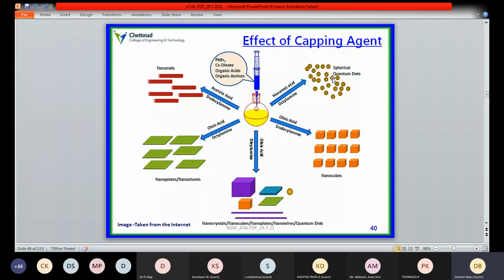If we can use various acids and amines, we can easily get rods, platelets, and cubes. If we use oleic acid and oleylamine as capping agents for preparing this perovskite system, and control the reaction time from 5 seconds to 1 hour, we can easily get spherical quantum dots to three-dimensional bulk crystals. The traditional methodology is the hot injection method. These are the simple methods to fabricate these perovskites.